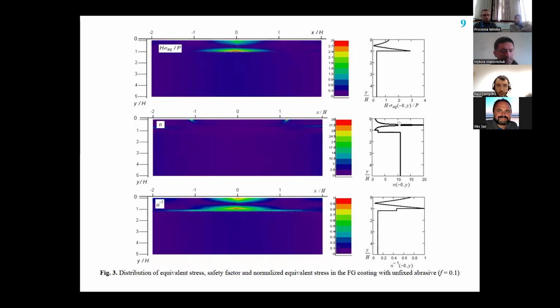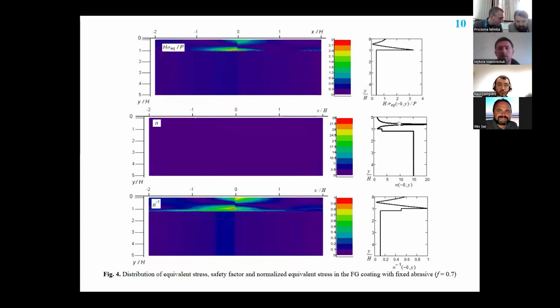On slide 9, we have the result of evaluation of the equivalent stress, safety factor, and normalized equivalent stress in the functional gradient coating with unfixed abrasive. We made the calculation with a small value of friction coefficient. And the next slide presents the similar result for the bigger friction coefficient. As we see in Figures 3 and 4, the stress state is concentrated in the vicinity of the line of application of the local load, and the highest level of equivalent stress is observed in the case of fixed abrasive.